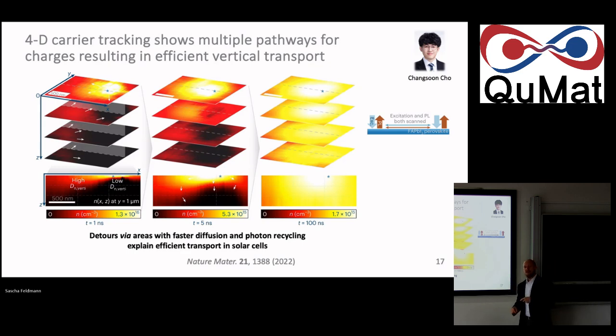And overall, across the excited state lifetime of the material that we have at hand, and the trap density it has on average, etc., we almost quantitatively collect all the charge carriers. So that's good news. This basically, again, rationalizes how we can get away with being so messy in the way we make the material. Yes, there are locally worse grains, but then there are also better ones. And overall, the performance is high enough that globally you extract the charge carrier typically within the lifetime of the excited state. So that was very reassuring news for people that want to make use of this solar cell stack. And that was kind of the second mapping story of the day.